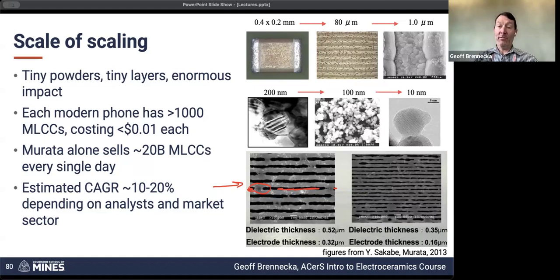If this were the other way around, and it were the electrode that we're shorting through the dielectric, then that would be a real problem because it wouldn't be able to operate at all. And so these are just showing a couple of examples way back from 2013, comparing half micron to a third micron, so 350 nanometer layer thicknesses, 12 years ago. So you can imagine where things are now as that scaling has continued.